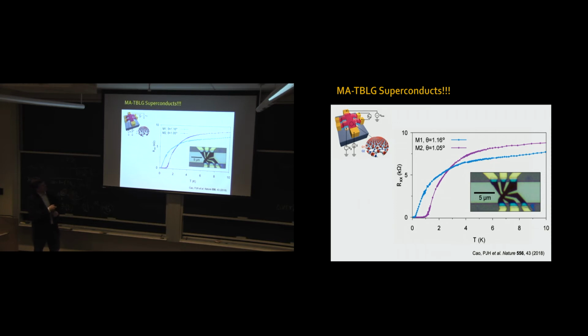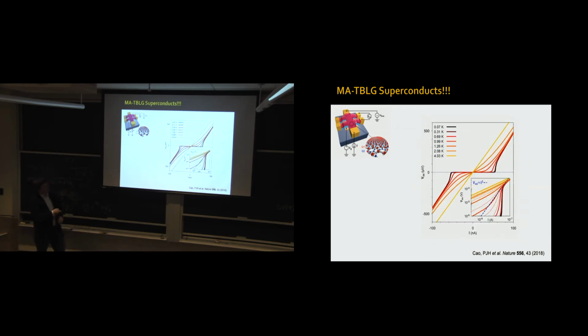The resistance versus temperature experiences a dramatic drop of several orders of magnitude, below our noise floor. This thing has zero resistance at low temperature. You can measure the VI curves, so you can run a substantial current through your device without any voltage drop in your device. You can do any test that you want of two-dimensional superconductivity. This is a two-dimensional superconductor.